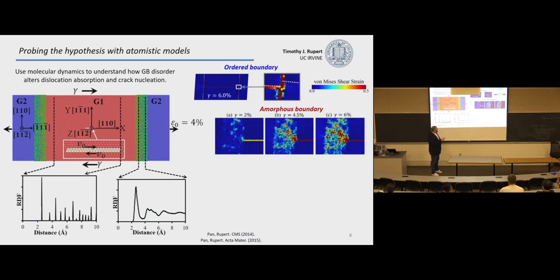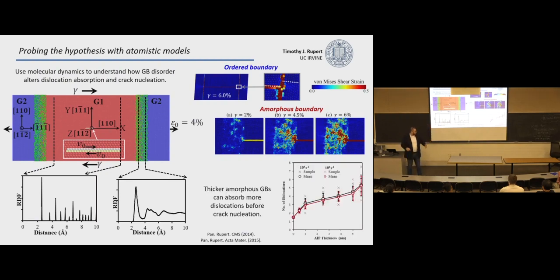When you have an ordered boundary, you get these red regions, which are high strain regions, so that dislocation is absorbed and accommodated, but it's in a relatively thin region at that boundary. Whereas in the amorphous region, you have this thick region that can co-deform and accommodate that stress over a larger volume. The thing that matters in terms of properties is you can look at the number of dislocations you can absorb before a crack forms and see that it's a function of the thickness of that amorphous intergranular film. So if you add an amorphous intergranular film and keep making it thicker and thicker, you can absorb more and more dislocations. Bringing this back to properties, it means you can survive higher strains.